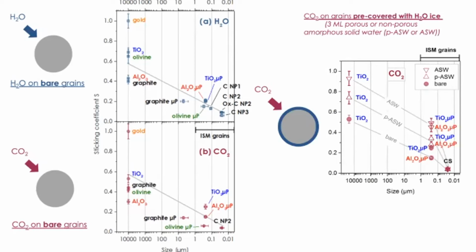And I have reported in that figure the case of TiO2, for instance. So if TiO2 is covered with water ice, you see that the sticking coefficient of CO2 is close to 1, as reported previously by Vidali and any studies that have been done so far on this issue. For ice that's porous, actually, the sticking coefficient is a bit lower, and this was also reported, I think, by Jennifer Noble and Helen Fraser a long time ago with infrared spectroscopy.